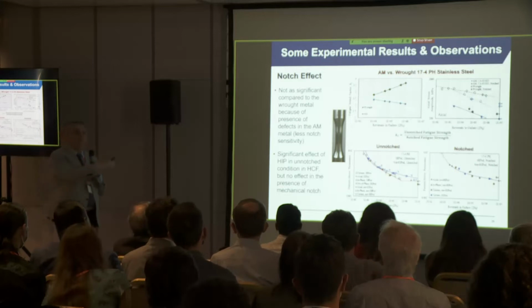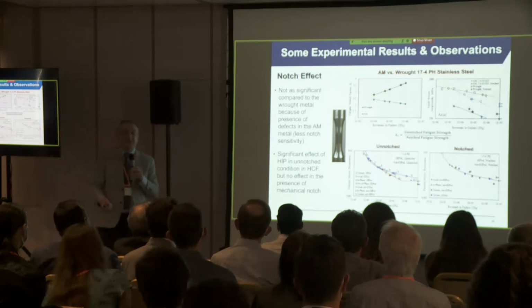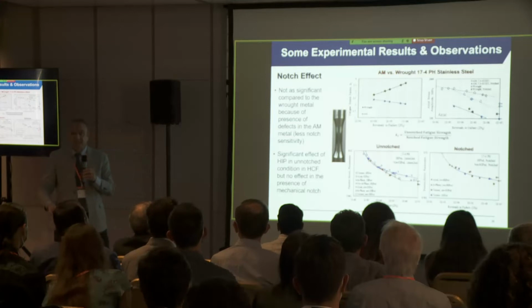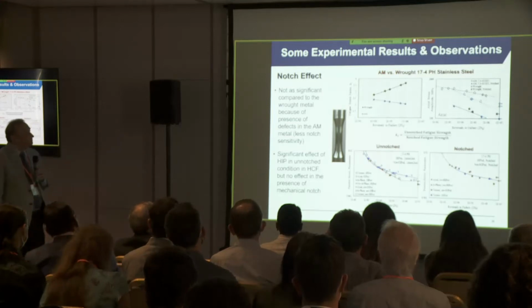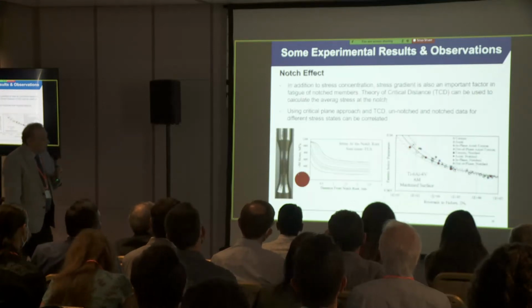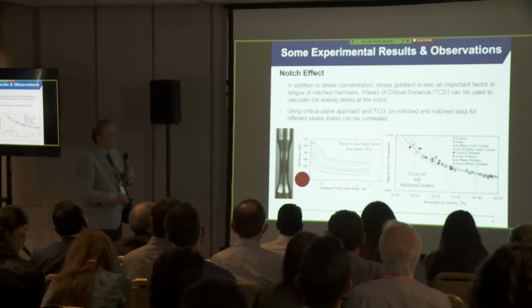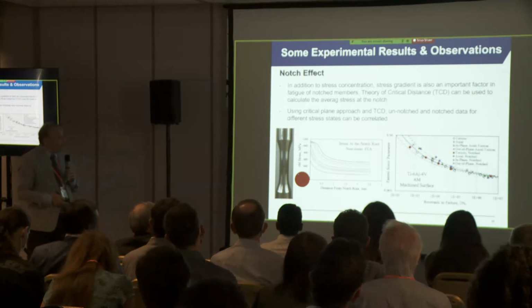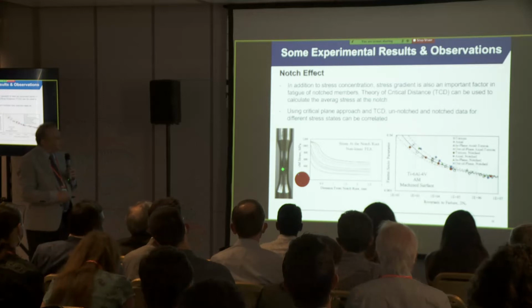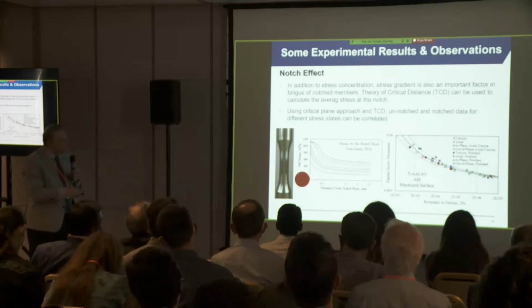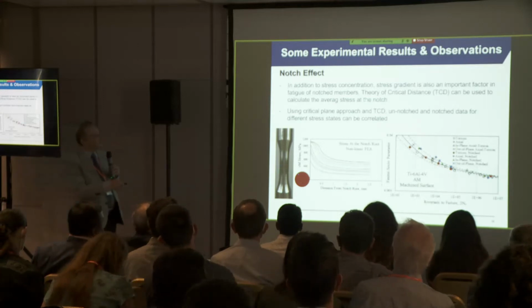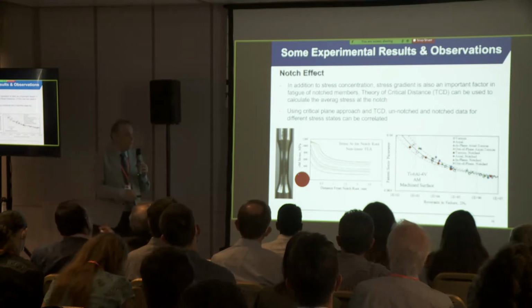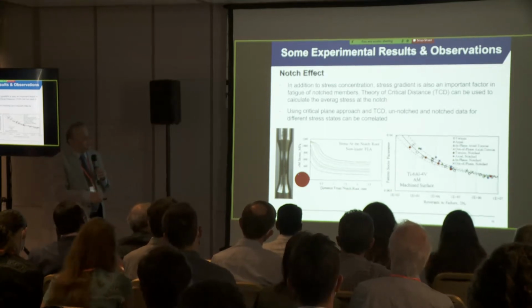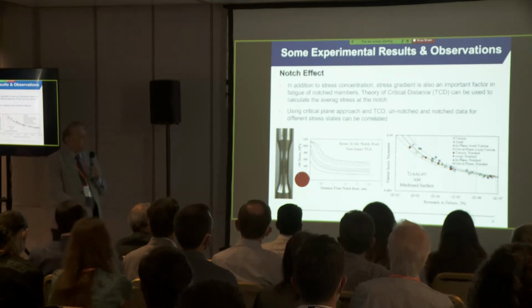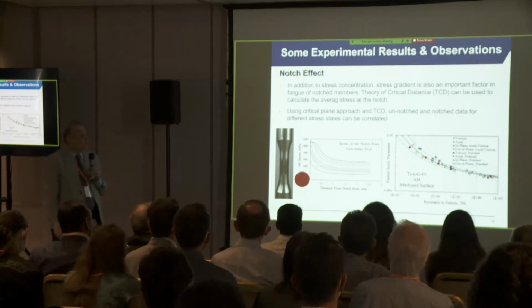The reason is that the defects are there. So it's not just the mechanical notch, but the defects that drive the damage process. But you can take into account the effect of the notch and the gradient of the notch. So if you look at this hole, there is a significant gradient. You can use theory of critical distance along with the right critical plane approach. Again, you can correlate very nicely all the data under different states with or without the notch.